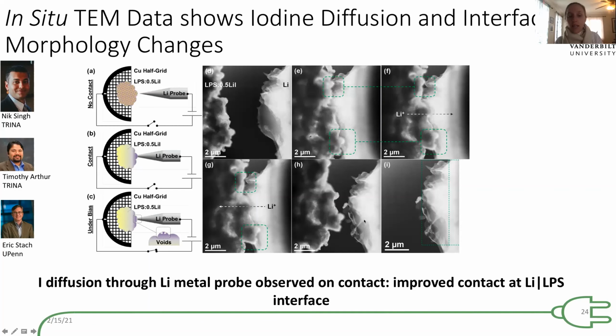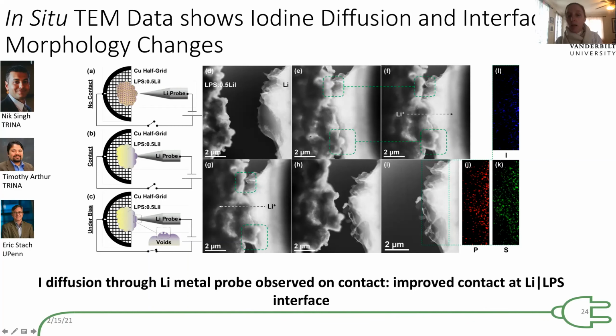Upon taking the lithium metal probe out and doing EDX, I see the presence of well-dispersed iodine in my lithium metal, which supports our hypothesis that iodine does indeed flow to the interface and in fact flows into the lithium metal, which provides better wettability of our lithium metal and suggests that the interface is ionically conducting. But we also see this pore form that's an irreversible entity at this solid upon lithium metal contact.